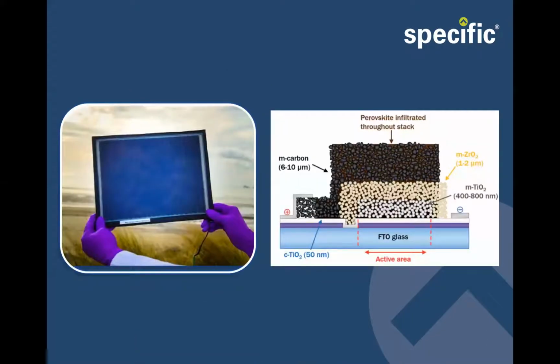The printed solar module shown here contains many solar cells which are side by side and is made up of multiple layers which are spray coated, printed and syringed in place. These layers include fluorine doped tin oxide, which is a transparent conductive layer, titania, which is a white pigment usually used in sun cream and even in your chicken nuggets, but here is used as an electron transport material. Zirconia, which is typically used in ceramics and dental implants, but here it's used to block the electrons, followed by conductive carbon, which includes graphite as you usually find in your pencils. Here it is used as an electrode. Then finally, a perovskite solution is infiltrated through all of the layers, which is the light harvesting material.